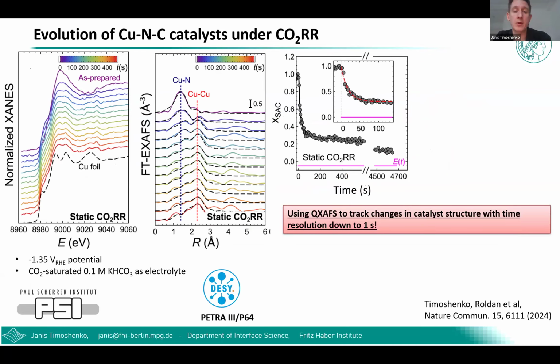So by using this operando quick EXAFS method, where again we can measure this process with a resolution of up to a few seconds, we can track very nicely how this formation of the metallic copper-copper bond occurs in this material and how this cationic copper-nitrogen bond is gradually diminished during this CO2 electroreduction experiment. We can quantify this transformation. We can extract information about how many of these copper species remain in the cationic state and how many of them are converted into metallic clusters.